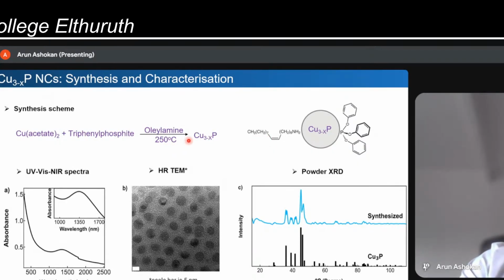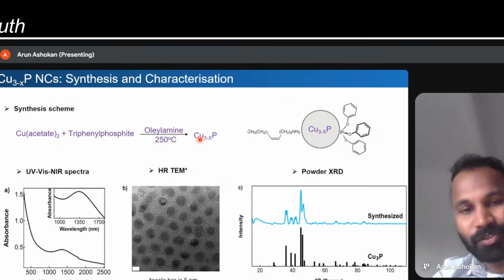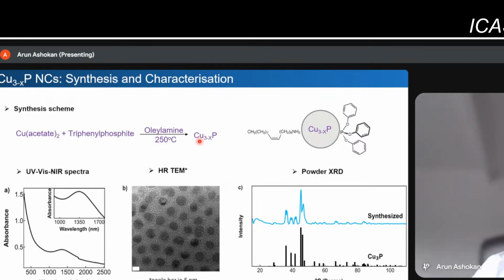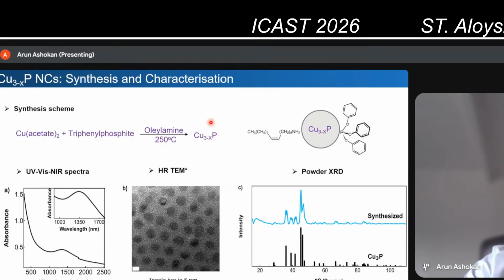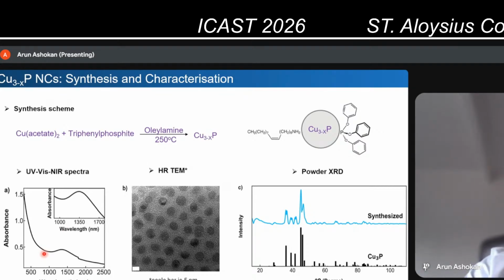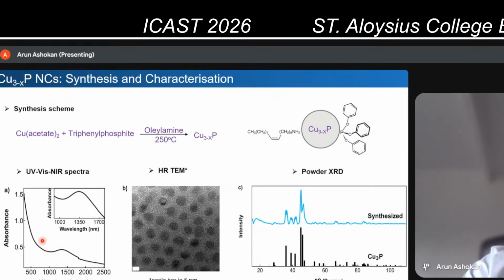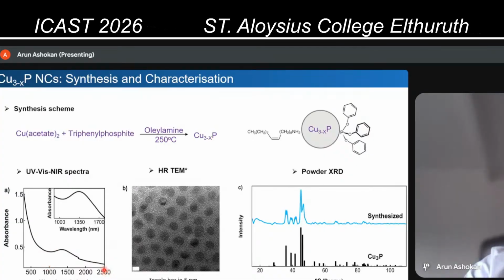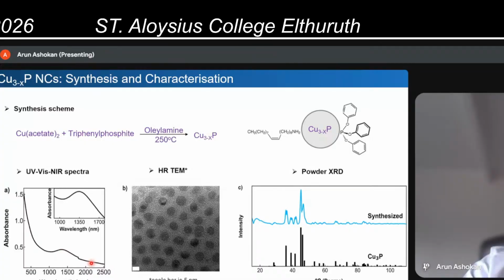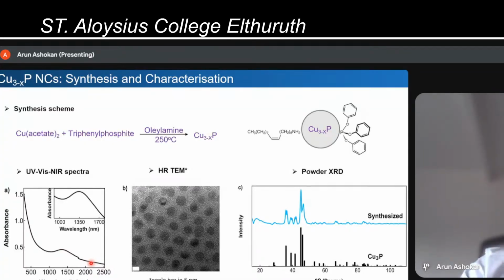So basically, you'll get a black colored solution after this reaction, which is a colloidal solution of copper phosphide nanocrystals. And if you take the absorption spectra or the extinction spectra of this solution, you can see that between 1000 nanometer and 2500 nanometer, there is a broad absorption. This absorption comes from the plasmon.